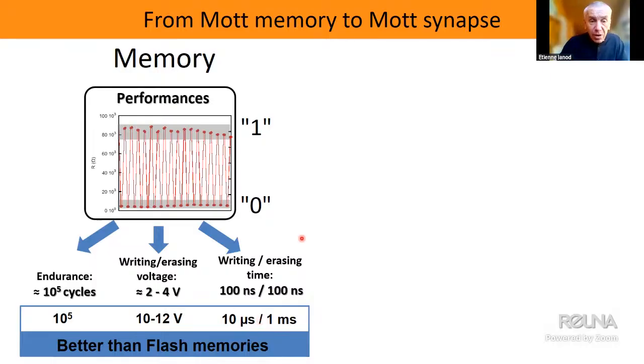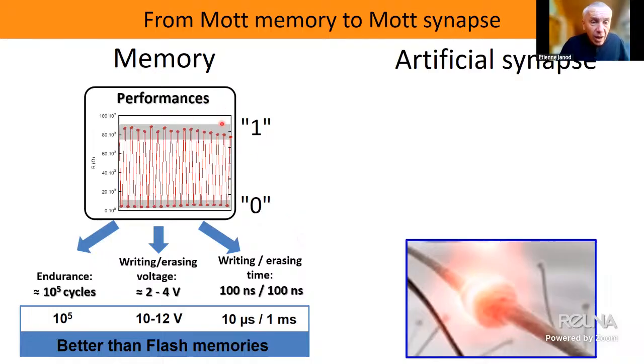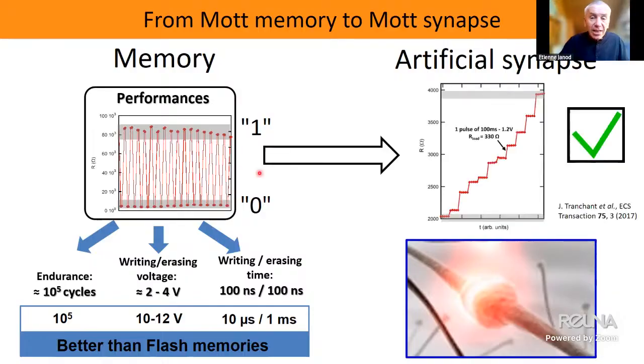Okay, this is it for memories. But what is interesting is that when you are able to get a memory out of it, you are not very far from being able to build an artificial synapse. An artificial synapse is almost the same as a memory, except that instead of stabilizing 2 levels of resistance, you want to have a continuum of levels between a maximum and a minimum. And you see that in this experiment, we have shown that it is possible. So clearly, we have a proof of principle that we can implement artificial Mott synapses.